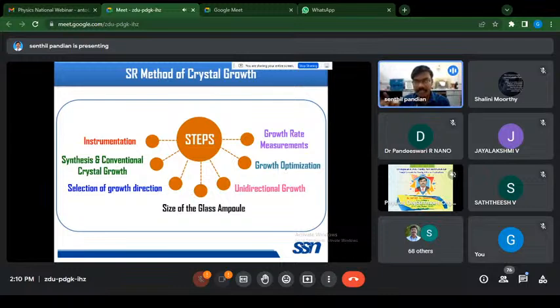Otherwise, after this, 41, 42, is a very high temperature, so the solvent evaporation rate will be very high. We cannot grow good quality single crystals in this SR method. So 40, 39, 30 will be all right for all the solution growth crystals.